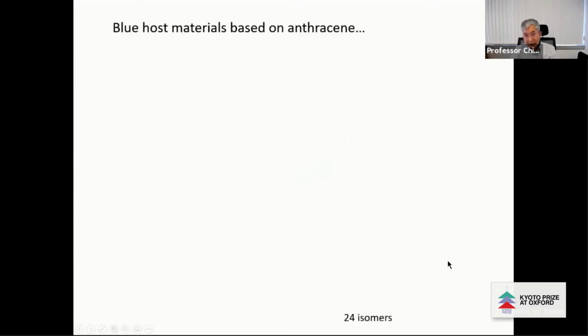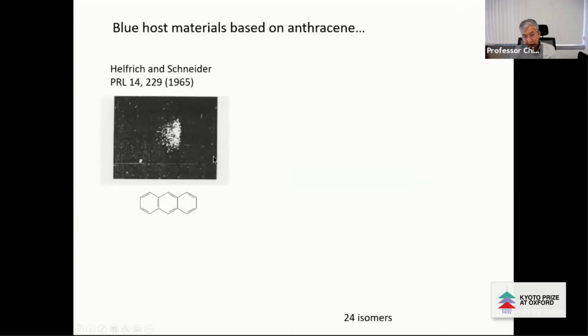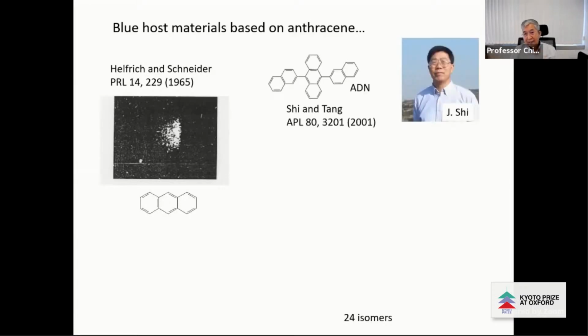So going a little bit into materials, the blue host material based on the anthracene. You remember this paper that I mentioned in 1965? It's an anthracene. It's a good material with very good quantum efficiency for the blue light. And so we took it in 2001. We published a paper in the APL. We just added two substitutions to it. We call this molecule ADN, and Jiming Shi is the person responsible for making this material.